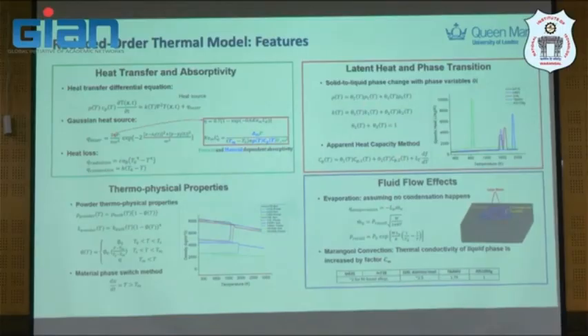You have the phase of the gas and the powder, and we try to calculate or understand how actually this is a way to incorporate the thermophysical property. It's just a model that we try to do, and then take into account the powder, and the fluid flow effect from the empirical relation. Again, this is not ideal, but it's something we do to take this into account in the heat model, and also take into account the Marangoni convection in the thermal conductivity of the liquid phase here. So all this thermophysical property, latent heat of phase transition, and fluid flow effect has been taken into account.